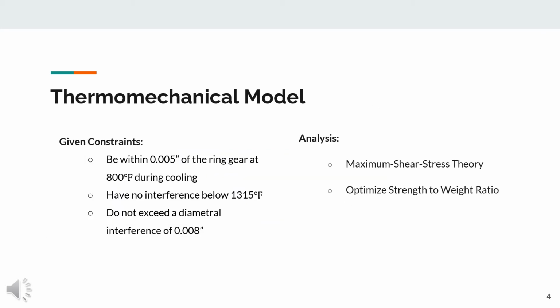Using the equations given in the previous slide, we created a thermomechanical analytical model. This model is based on constraints given to us by our sponsor AeroGear, of which they wanted us to be within 5 thousandths of the ring gear at 800 degrees Fahrenheit during the cooling process. They didn't want any interference below 1315 degrees Fahrenheit, and at any given temperature they did not want us to exceed an interference greater than 8 thousandths.